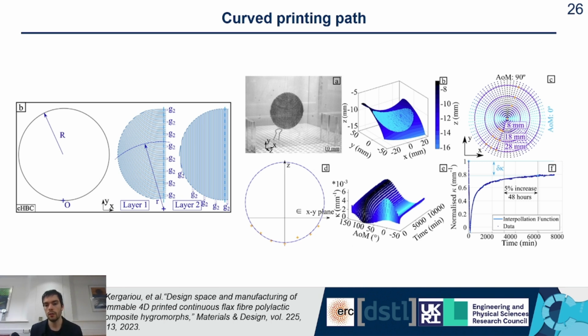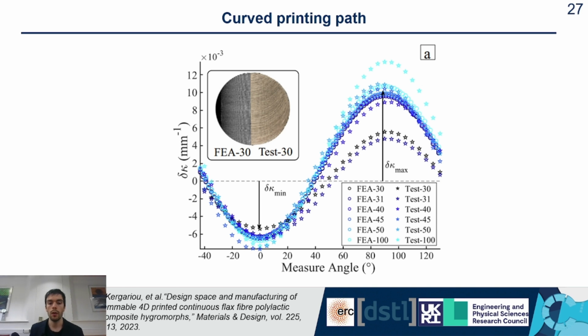And so we could measure the curvature against the different angles and against the time, as you can see at the bottom center of your screen. So we obtain this normalized curvature for different times and angles of measurement. This curvature is plotted against the angle of measurement, so the different angles in the radii of the specimen. This graph shows that basically the more straight the fibers are, the more actuation you get. So we were not able to improve the amount of actuation by curving the fibers, but we were able to control the actuation by curving the printing path. And that's another way of controlling the actuation, basically controlling the printing path of your soft robots.